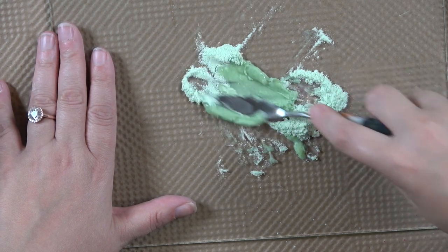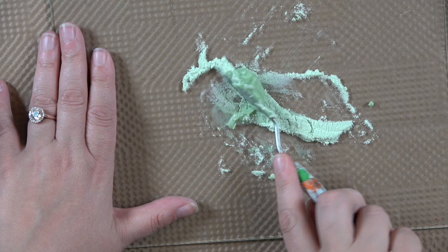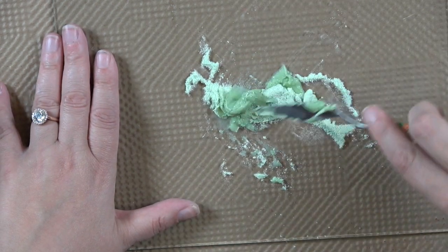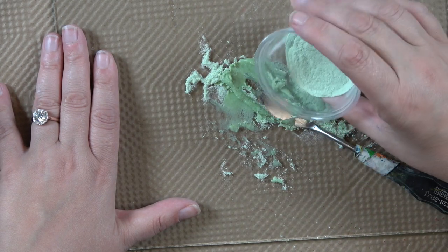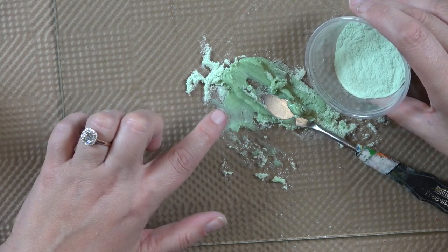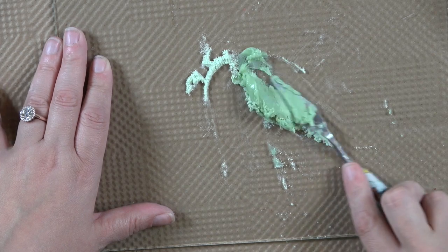the more gel that you have in the powder, the glossier it's going to look. That's not what we want. We want this powder to look like the color that's in the jar. So if we bring this color in right here, that's light, and look how dark this is right now, because there's too much gel in here, okay? So let's get it all mixed up and see what we come up with.